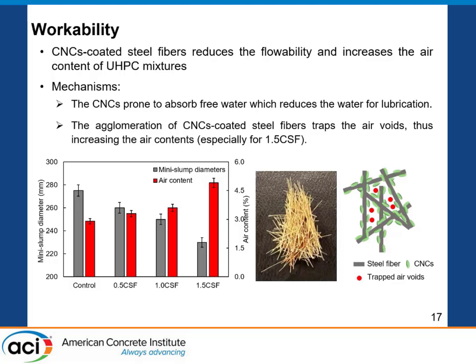The reason is that when we use the CNC to treat the steel fibers and dry them in the oven, they stick together because of the very high concentration of the CNCs, and the bond is so strong. When we use a kitchen mixer to mix it, we cannot disperse it very well or break those bonds. So I think that is a reason, and also because of this agglomeration of the steel fibers, we have a significant increase in the air content when the CNC concentration is more than 1%, which is 1.5% in our case.